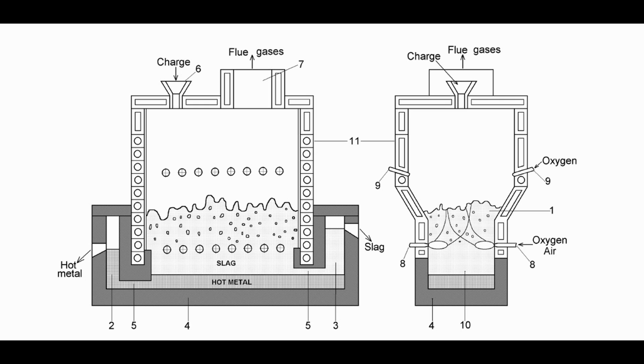The bath of melting slag is blown with an oxygen-air mixture through the lower tuyeres positioned below the slag layer. The tuyeres have a simple structure and prove to be reliable in operation. They ensure the required agitating power of the slag bath. Getting into the agitated slag that contains coal, iron-bearing materials are reduced. Iron, produced by the reduction, becomes enriched in carbon. Drops of melted metal precipitate under gravity on the furnace hearth. Thus, three melted layers are formed in the furnace: the layer of metal on the furnace hearth, the layer of calm slag between the metal and the lower tuyeres, and the layer of agitated slag, the reaction zone.